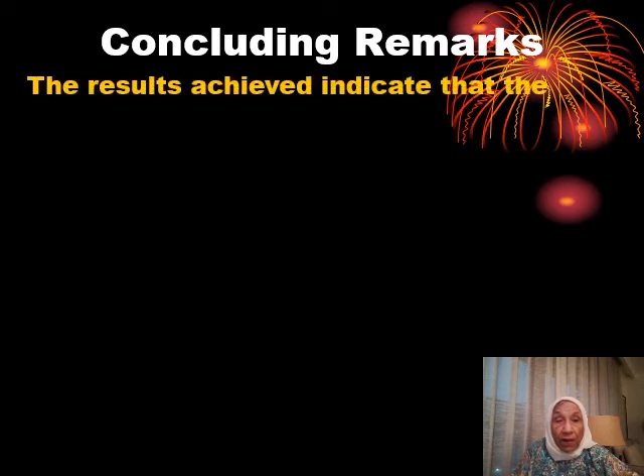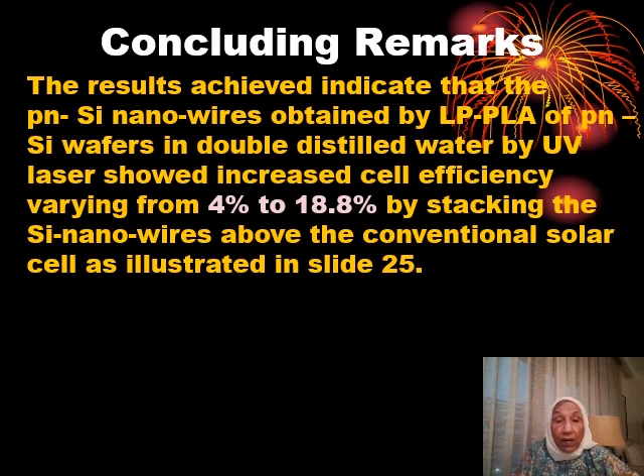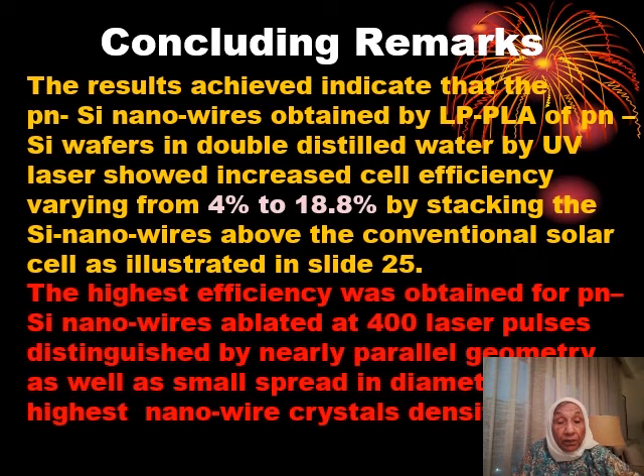We can say the results achieved indicate that the PN silicon nanowires obtained by the liquid phase pulsed laser ablation of PN silicon wafers in double distilled water by UV laser showed increased cell efficiency, varying from 4% to 18.8% by stacking the silicon nanowires above the conventional solar cell, as illustrated in slide 25. The highest efficiency was obtained for PN silicon nanowires ablated at 400 laser pulses, distinguished by nearly parallel geometry as well as small spread in dimensions and the highest nanowire crystal density.